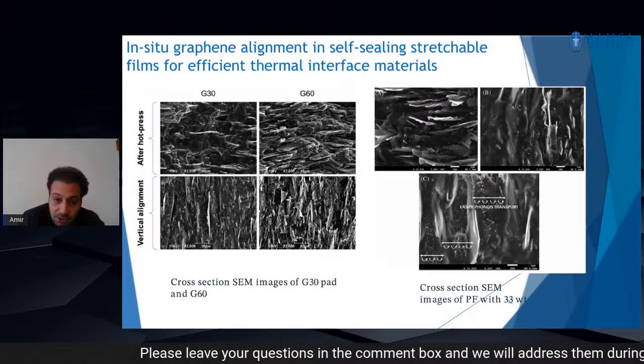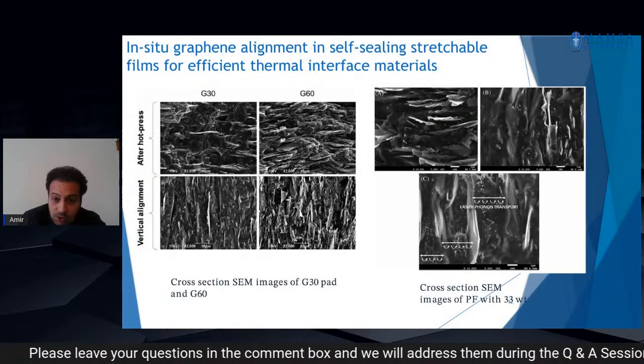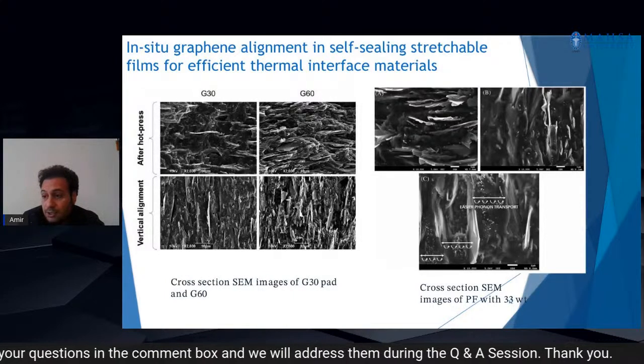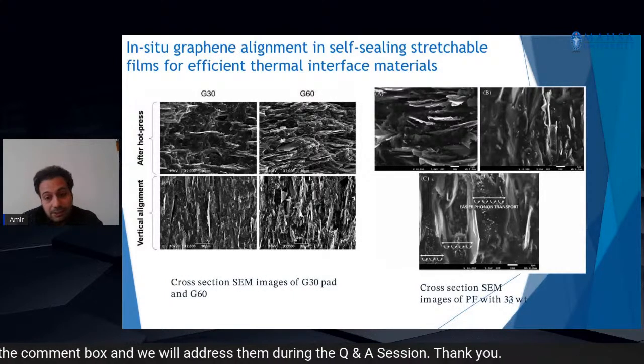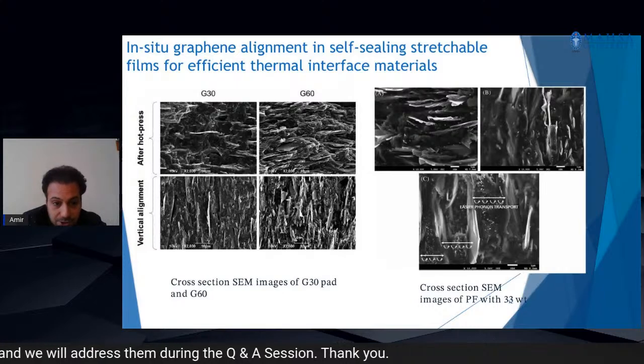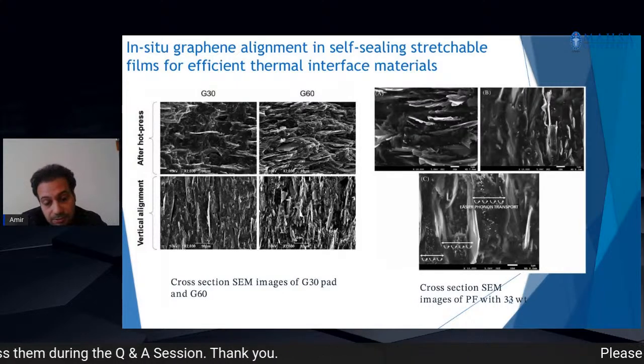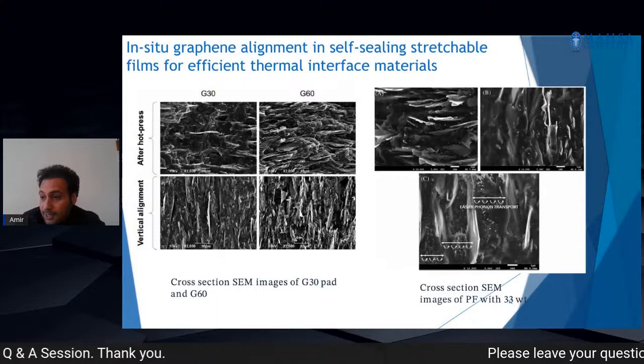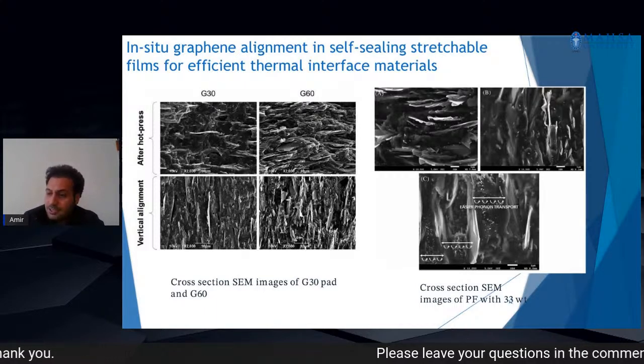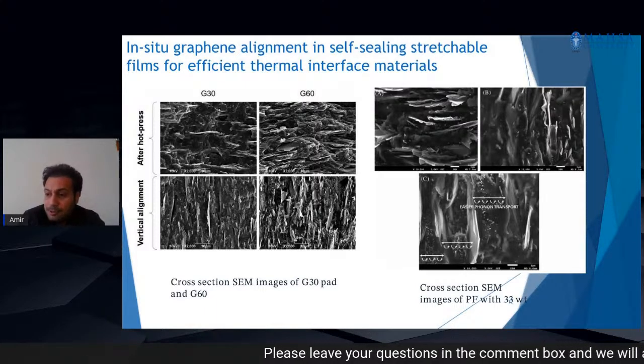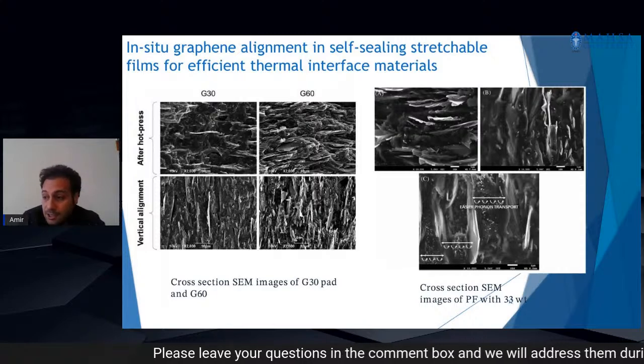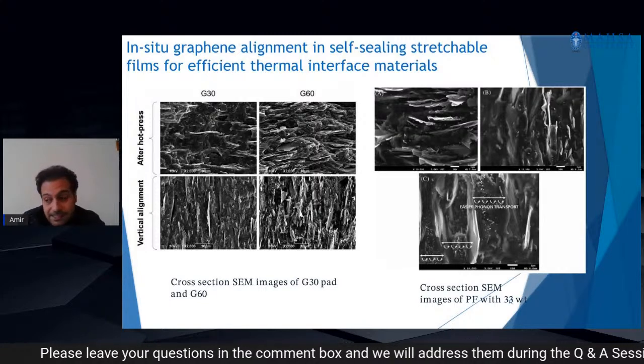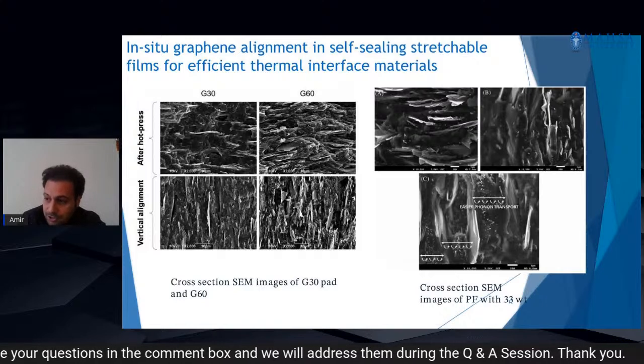And after the hot pressing on the left one, and on the right one after vertical alignment, that is clearly visible in the surface of the samples. And at the bottom, C is the cross section SEM image of vertically aligned PF with 66 percentage.